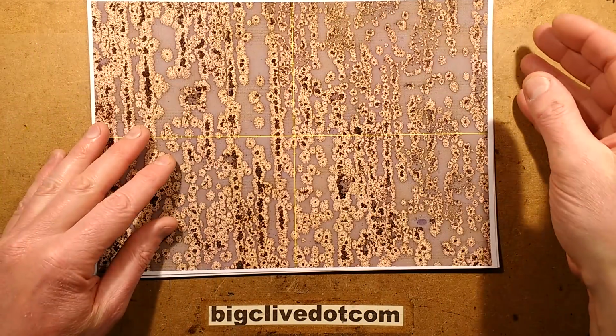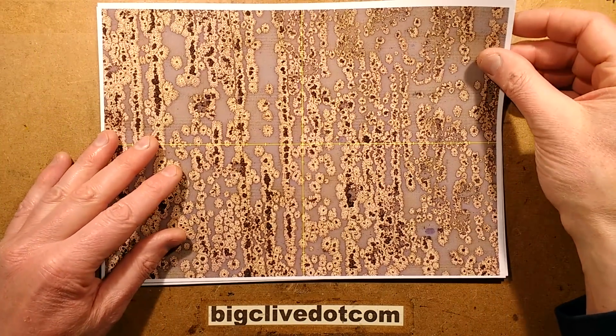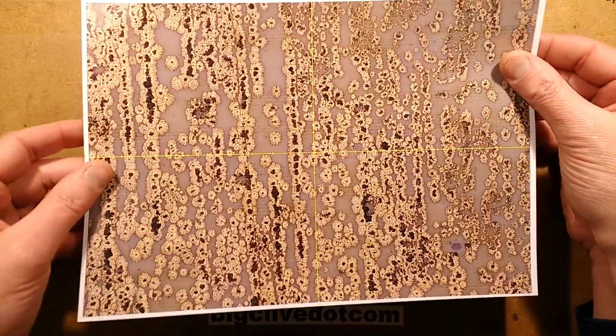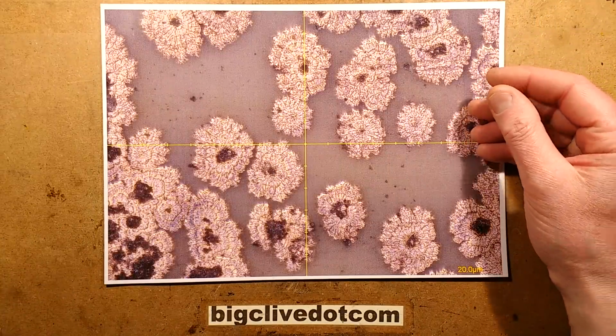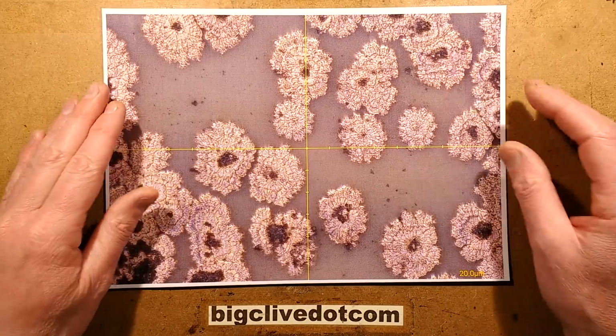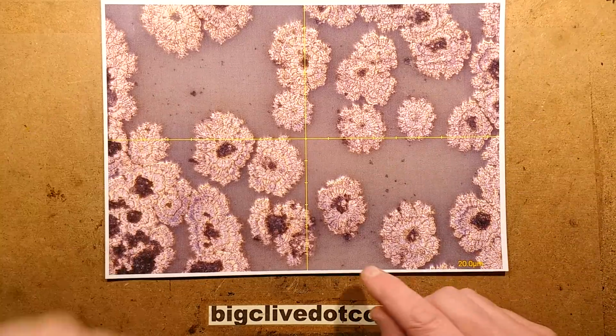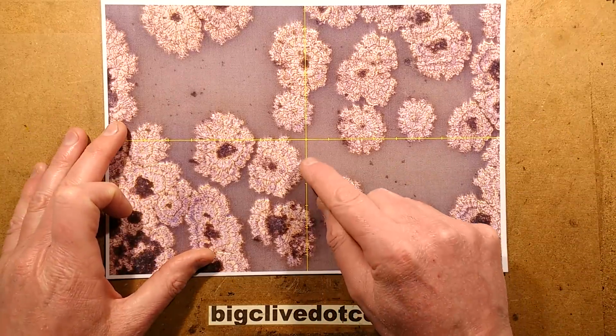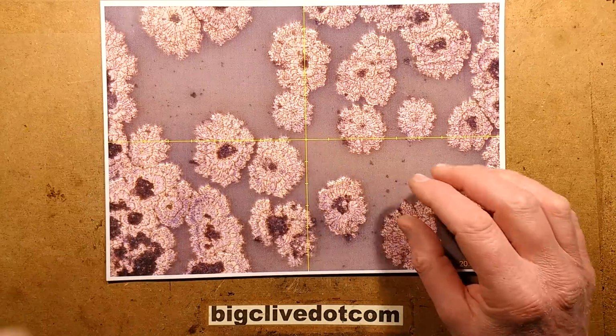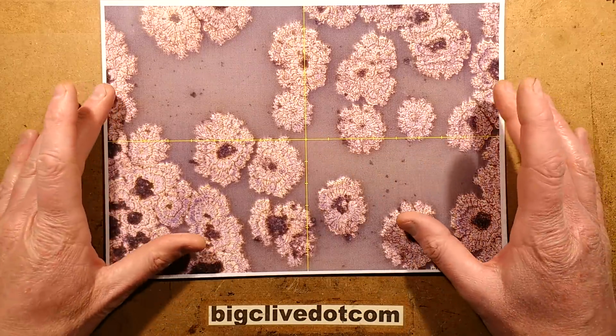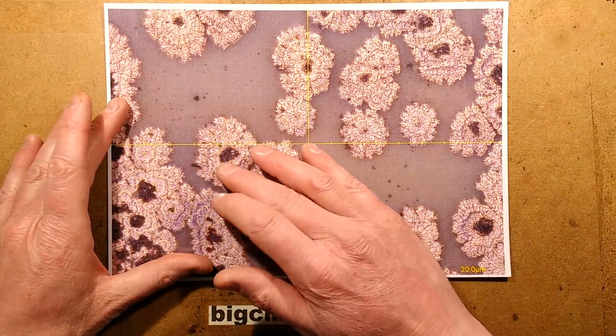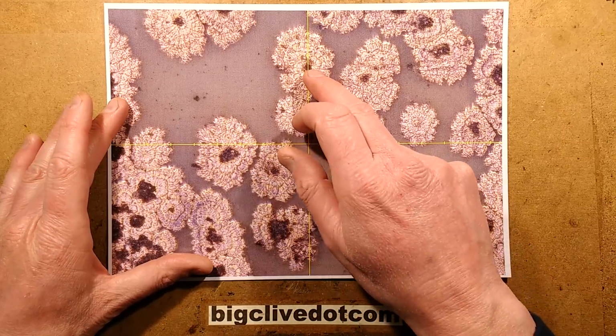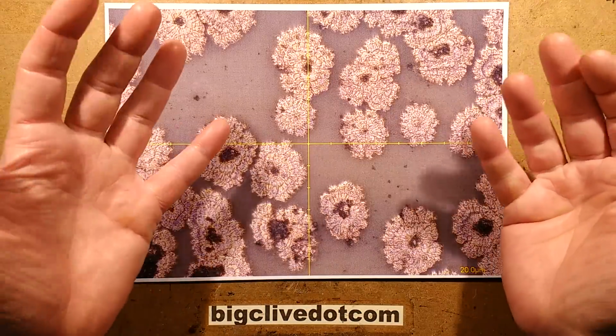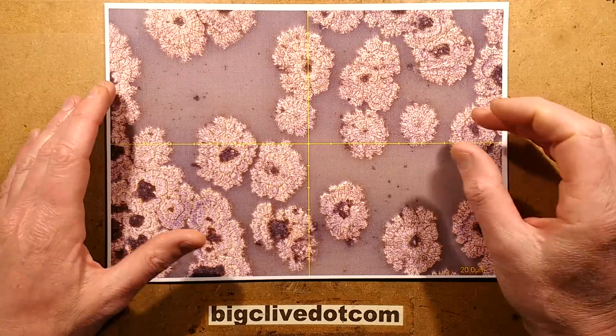that separator. But here's where it gets really interesting, because while those give a bit of information, what really shows the maximum information here, this is a 20 micrometer. I'm not sure, I guess it's 20 micrometer per point here. And what it shows here is these little islands of copper all have this pore, and it's a very visible three-dimensional pore that's going through the material.